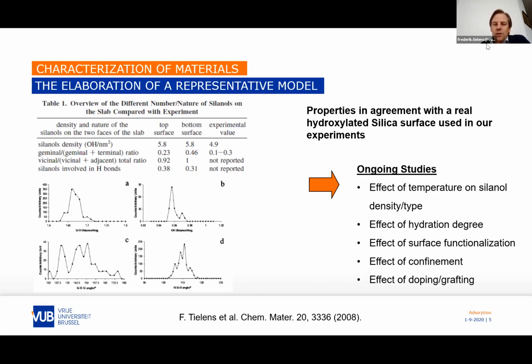So we used one, and we tried to mimic the experimental results in our models, and this is done by doing it by hand and then relaxing it. We opened ring sizes, siloxane rings, which means that we dehydrated and hydrated by hand, placing the different hydroxyl groups before a relaxation. All this was then relaxed with molecular dynamics at the temperature that we wanted to use for our application. This model contains about 260 to 300 atoms.